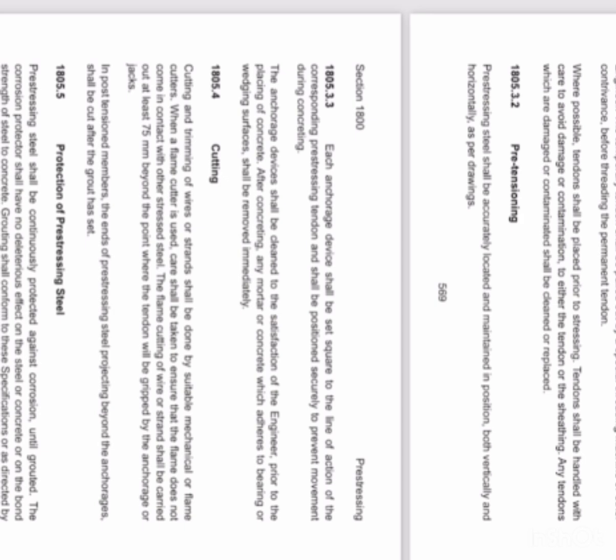Cutting and trimming of wires or strands shall be done by suitable mechanical or flame cutters. When a flame cutter is used, care shall be taken to ensure that the flame does not come in contact with other stressed steel. The flame cutting of wire or strand shall be carried out at least 75 mm beyond the point where the tendons will be gripped by the anchorages or jacks. In post-tensioned members, the end of pre-stressing steel projecting beyond the anchorages shall be cut after the grout has set.